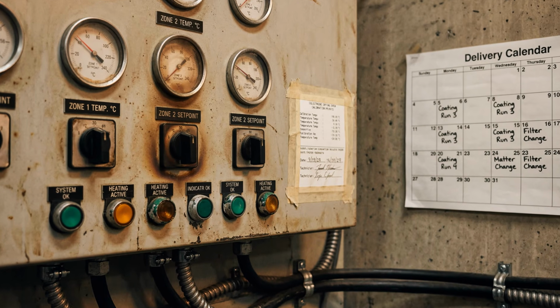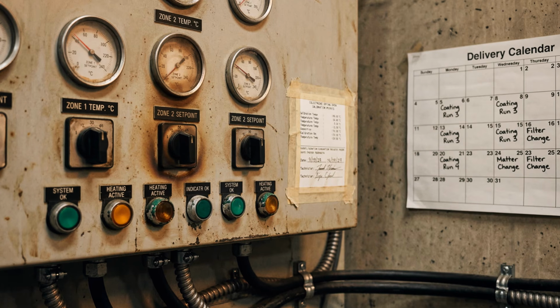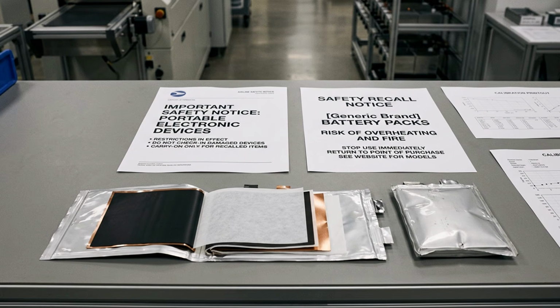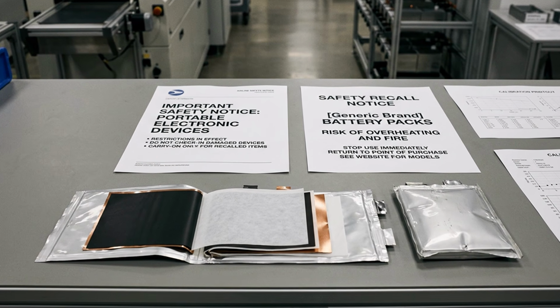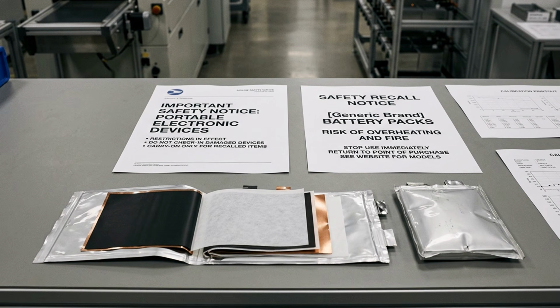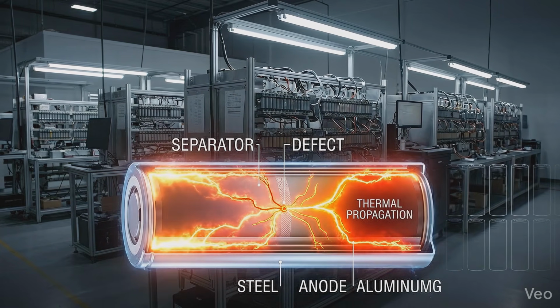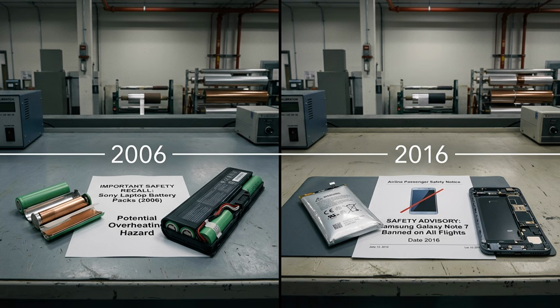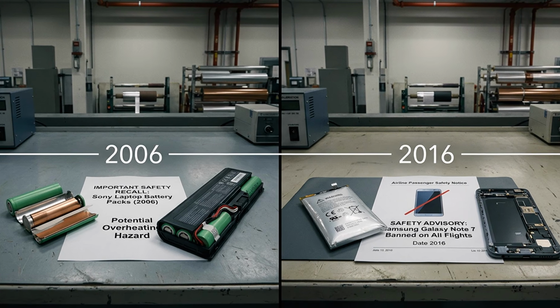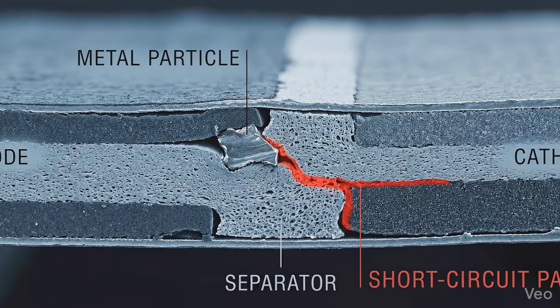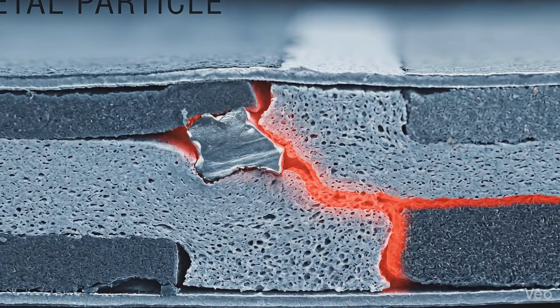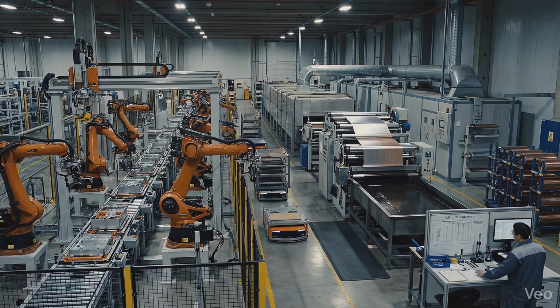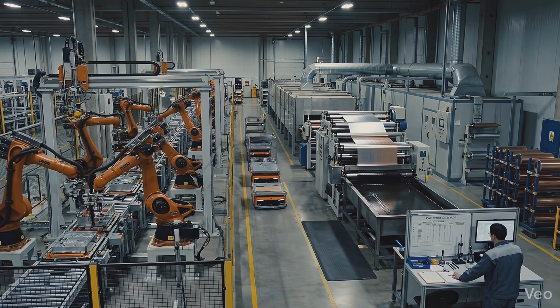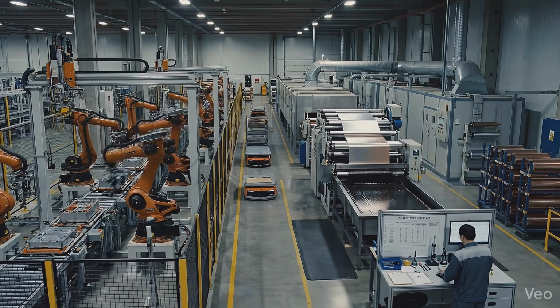This is what the Samsung SDI Galaxy Note 7 recall in 2016 pointed toward: potential manufacturing process control issues in cell production, where pressure to accelerate ramp-up collided with the unforgiving precision requirements of lithium-ion chemistry. The specific causal mechanisms remain debated, but the incident highlighted how manufacturing precision failures in lithium-ion cells can lead to catastrophic outcomes, a lesson that applies across the industry. And it echoed what the Sony laptop battery recall a decade earlier had already signaled. In that case, metal particle contamination was identified as a key contributor to internal short circuits. Both recalls underscored the critical importance of manufacturing process control in battery production, and how the failure modes live in the parts of the process that robots cannot simply be upgraded to fix.